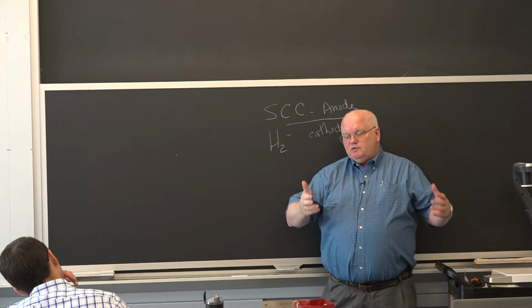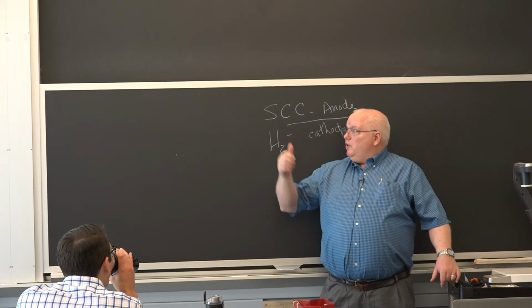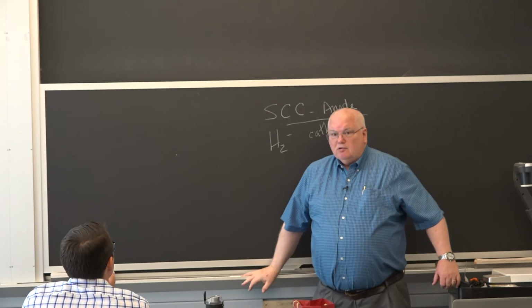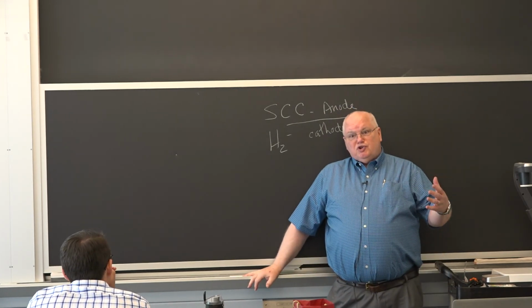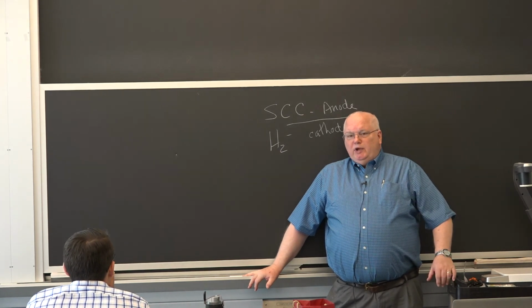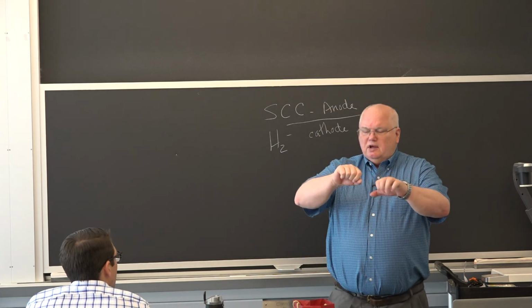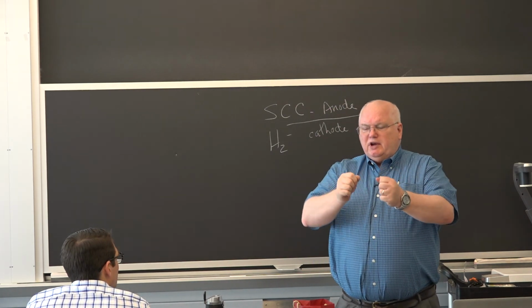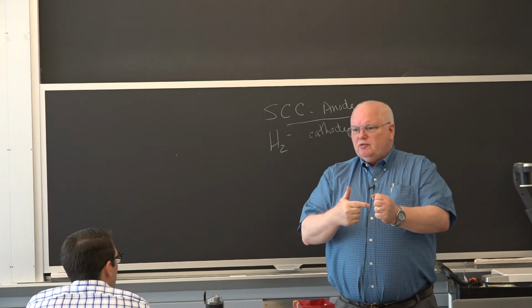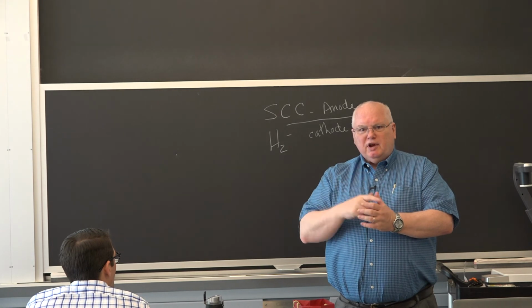And so the guys I was working with wanted me to do a test. We did a laboratory test. We made the steel the anode. Because in stress corrosion cracking, you're getting corrosion at the anode. Okay? We could not crack those. I mean, all you have to do is you just take a piece of carbon steel and you bend it into a U shape. This is a pretty sophisticated test. Put a bolt through the bottom so it stays in the U shape. Now I have a tensile stress on the outside of the bend, right?